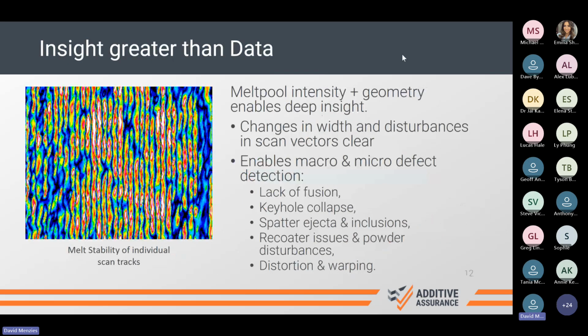So what we get on each individual layer here is melt stability. You can see there's different tracks going in the top to bottom direction there. That is the laser activity that's going across the melt pool. It's effectively a welding technique when you boil it down. What we're looking for is changes in the geometry of those and the intensity, which is effectively what we call a texture. Through that texture, we can then determine if there are any defects occurring. Obviously, in a single layer, that's interesting. But if you are seeing it in the exact same XY coordinate across several layers, then you know you've got a problem occurring that needs to be actioned as a manufacturer.